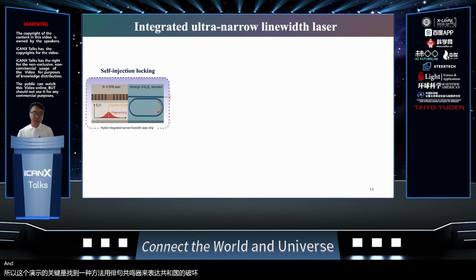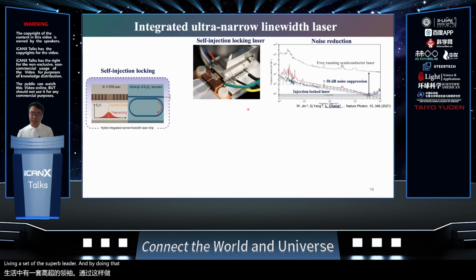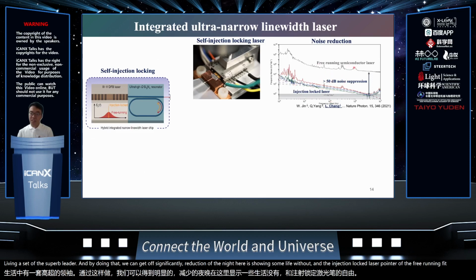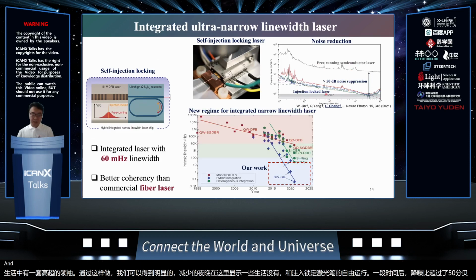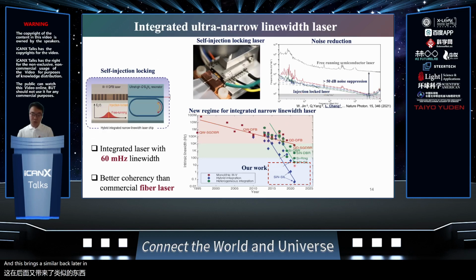One new mechanism we developed is the self-injection locking, which is to leverage the backscattering of the high Q resonator and to collapse the lasing state of the III-V lasers. By doing that, we can get a significant reduction of the noise. Here are some results: the injection locked laser, compared to a free running semiconductor laser, gets more than 50 dB noise suppression ratio. And this brings the semiconductor laser into a new regime of coherency on integrated photonics.